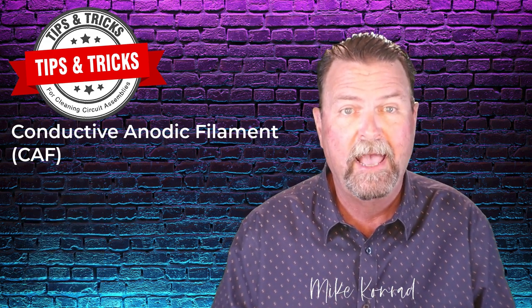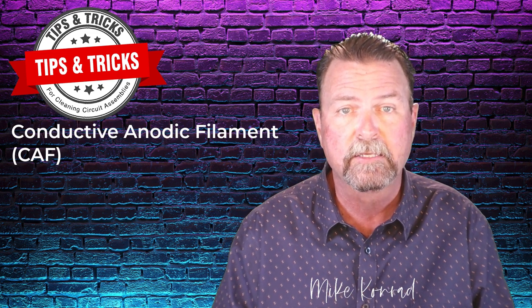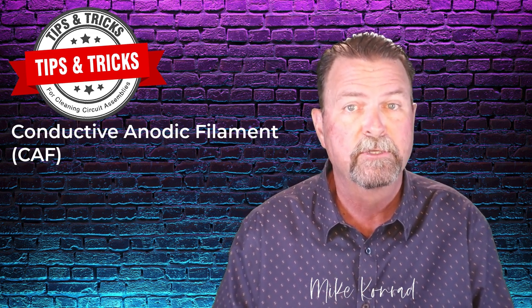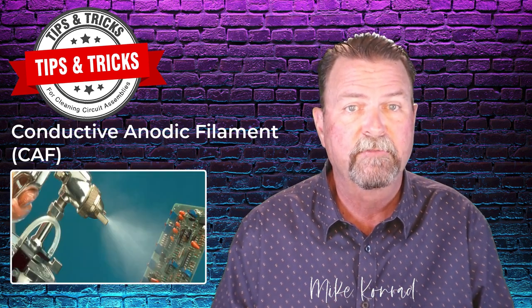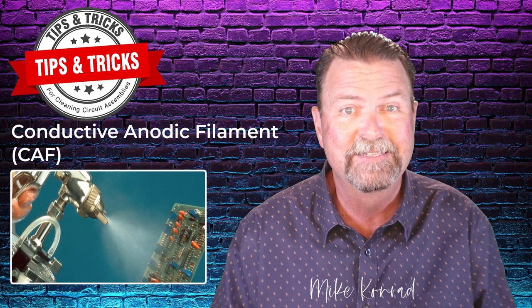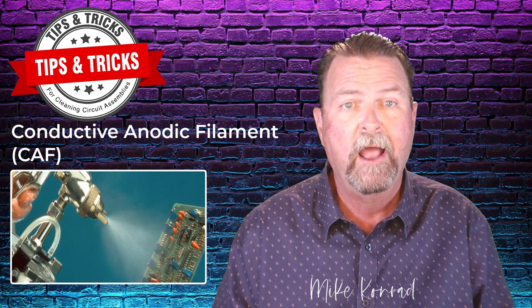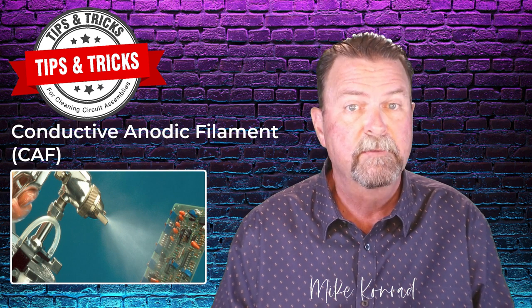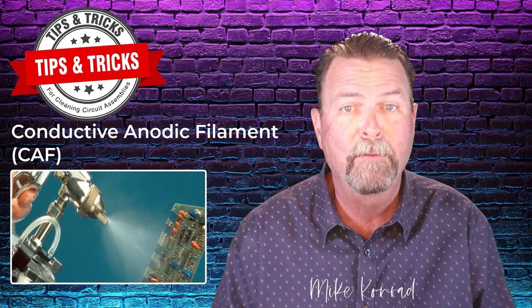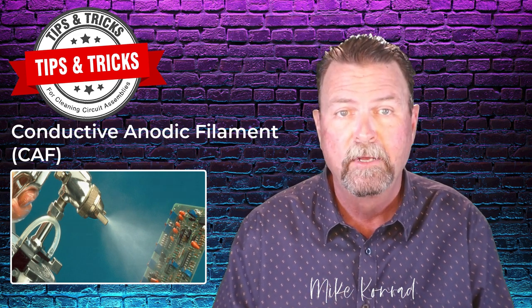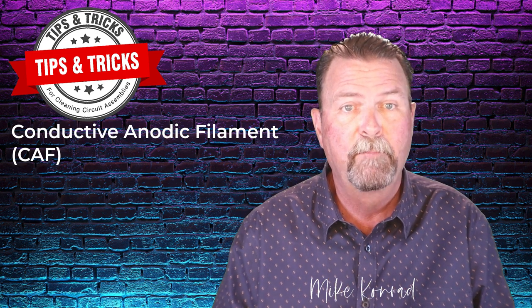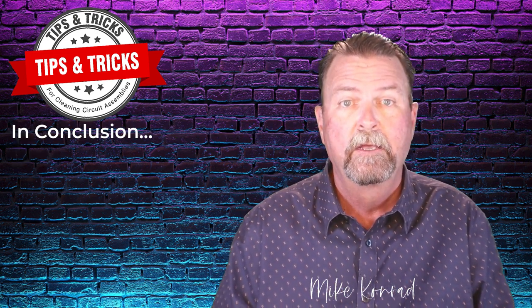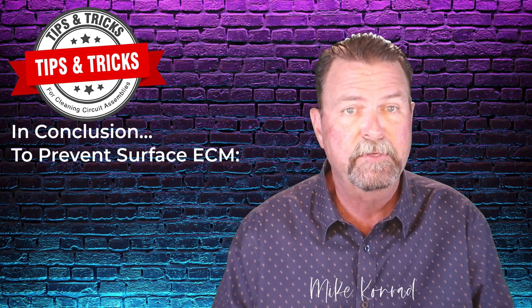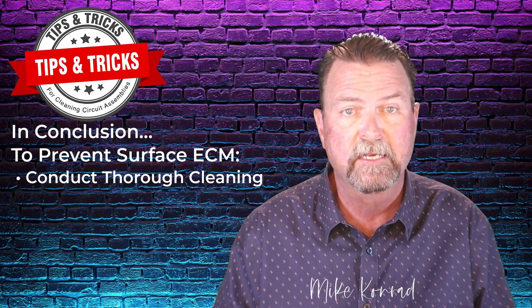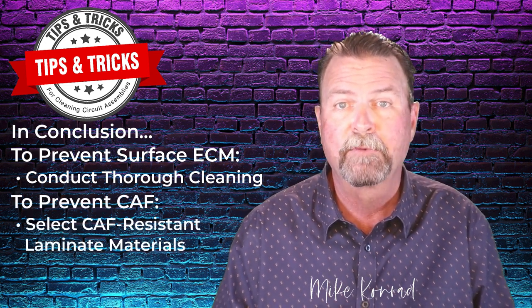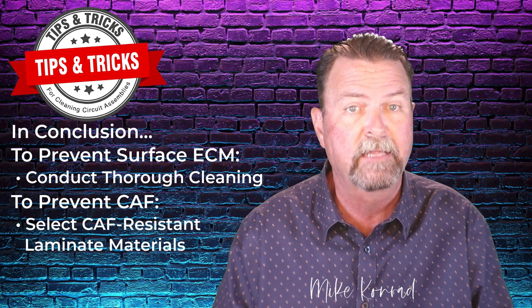For complete and permanent CAF elimination, it's best to ensure there are no pathways for the electrical bias, conductive materials, and moisture to exploit. Many assemblers believe the application of conformal coating will prevent moisture intrusion. This is not accurate. While conformal coating will prevent higher volumes of fluids from contacting the assembly, it's important to note that conformal coating materials are permeable, allowing small amounts of moisture to permeate through the coating. If CAF is a concern, select board materials that are CAF resistant. So to wrap up, to prevent ECM from occurring on the surface of the assembly, subject the assemblies to a thorough cleaning process. To prevent CAF, select CAF-resistant board materials, which reduce the possibility of gaps between the laminate layers.